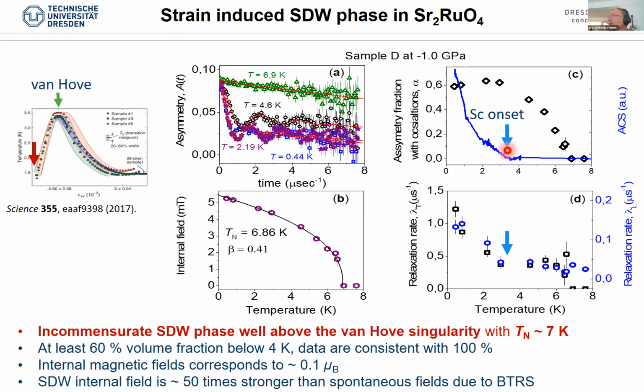Yes, there are some indications that in the AC susceptibility, we do see that there is an onset of superconductivity at roughly half of the Néel temperature of this magnetic ordering. And we also see some interplay of superconductivity, or hints of interplay of the superconductivity with the magnetic order, because this is the temperature below 3.5 Kelvin where the relaxation rate of our muon signal, the static line width, is increasing a little bit more. Nevertheless, I want to point out that since this magnetism is really much stronger than the time reversal symmetry breaking magnetism which we see, in our interpretation, this is a competing state and it's not the same kind of magnetism which appears in the time reversal symmetry breaking.